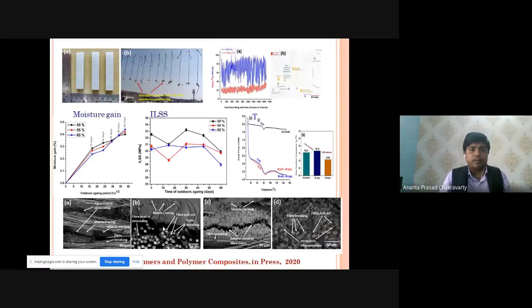Similarly, I designed these composites and exposed them to a normal environment, like on the rooftop, for up to 3 months. Up to 60 days I can see that moisture gain increases, but at 30 to 40 days the strength is at its maximum, for different volume fractions of fibers. I can conclude that these composites also sustain in our natural environmental exposures, where moisture exposure and temperature fluctuations are very crucial. This experiment was carried out in Bhubaneswar.